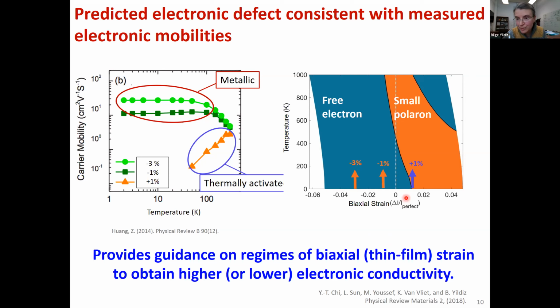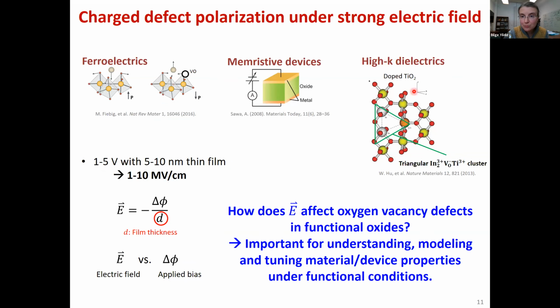And if the goal is to obtain more conducting films, compressive strain regime is the ideal regime. Whereas if the goal is a more insulating starting point, such as in high-K dielectrics, then the tensile regime is the desirable regime to work with. Okay, so that's one example of how the elastic strain in such devices can give rise to drastically different electronic properties. So now let's move to the effects of electric field, very strong electric fields, which are present in thin